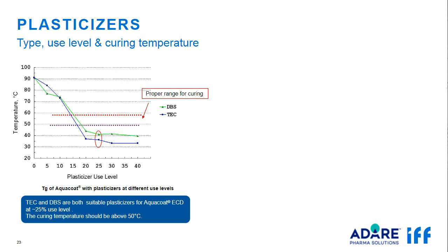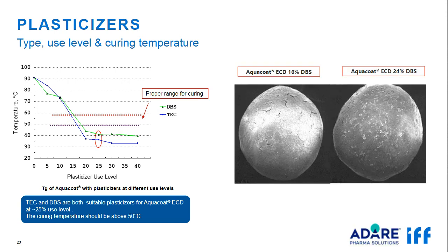At lower concentration of plasticizer, the polymer cannot form a continuous film, and the film would be brittle. We can see cracks on the coated pellets in this image, but at about 25% plasticizer, a continuous layer of the film without cracks is formed, as shown in this image on the right. Drug release from these pellets is robust, predictable, less variable, and slower than the release from the pellets with the defective film. So it is important to add a sufficient amount of plasticizer in the coating formulation and make sure the coating temperature is above the glass transition temperature of the coating.